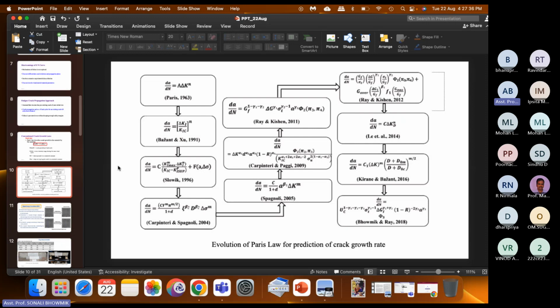clearly and in more detail, but here I'm just mentioning a few things: in the analytical area, when I'm talking about how to predict the fatigue crack propagation model, it depends upon multiple parameters, and it is very important to verify and validate those parameters, and to understand whether each parameter has a direct or indirect effect on the fatigue crack propagation model or not. This is a very rigorous study of each and every parameter, so that finally you come out with a refined or modified and robust model of fatigue crack propagation rate and fatigue life of a structure. So this is up to analytical, where people have already explored.